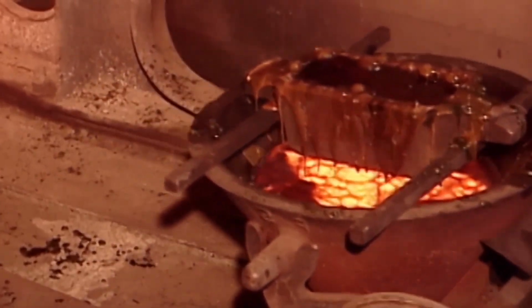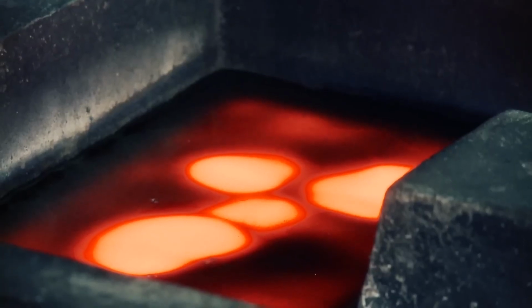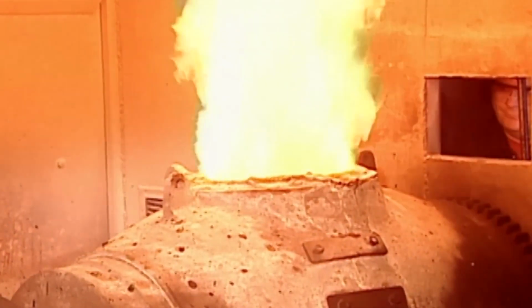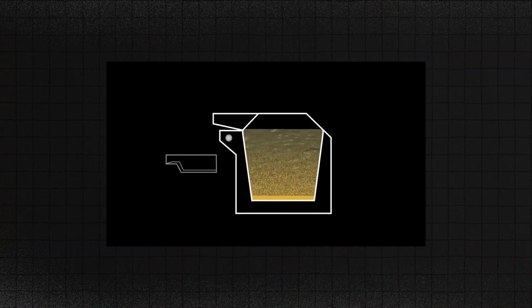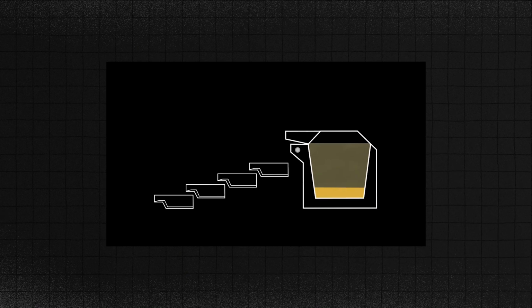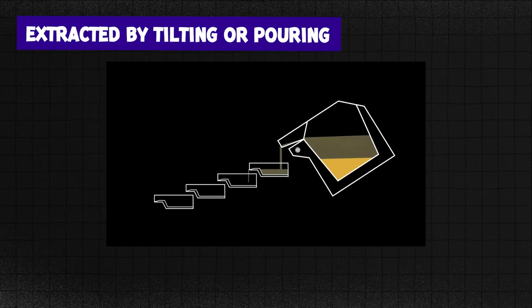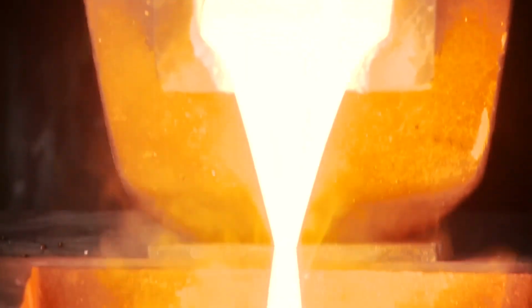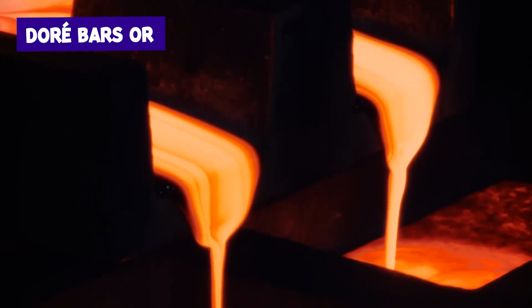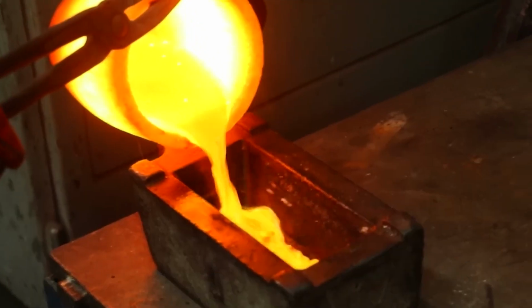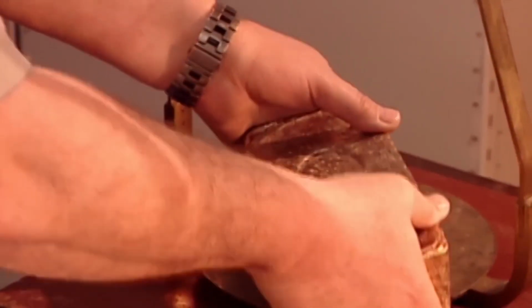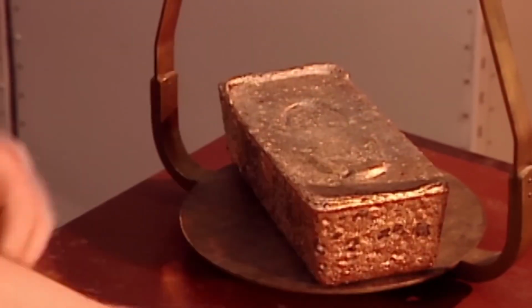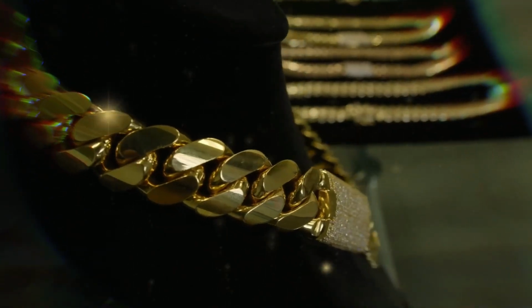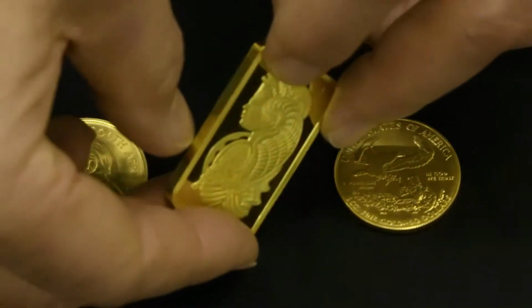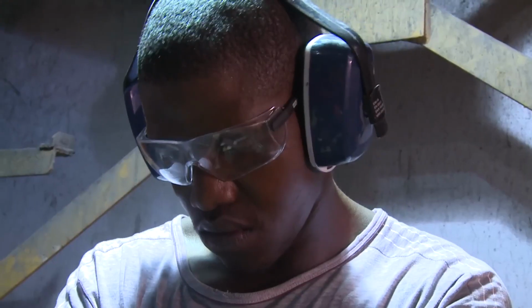Workers gather this slag and check it to ensure it contains no gold. If any gold is detected, the slag is returned to the furnace to remove all gold content. Once the gold has collected at the bottom of the furnace, it is extracted by tilting or pouring out the molten mixture. The gold is then poured into molds, forming doré bars or bullion. Notably, the doré bars or bullion are only about 80% pure after this process. To reach the international gold purity standard of 99.9%, further refinement is necessary.